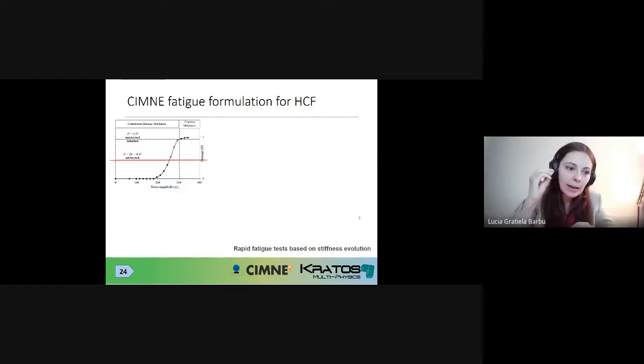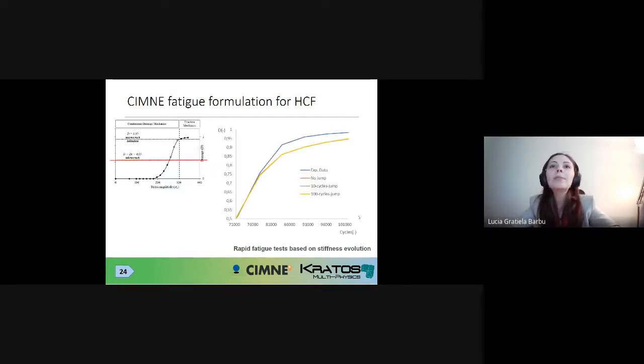Okay, it's not similar to the integration point damage that you would see in a constitutive law. And we wanted to see if at structural level of the sample we were able to obtain the same behavior. And what we've seen is that we've gotten quite a good agreement between the numerical and the experimental part. I have to say that here we only analyze the damage or the change in stiffness after a specific level of damage, which is 0.5.